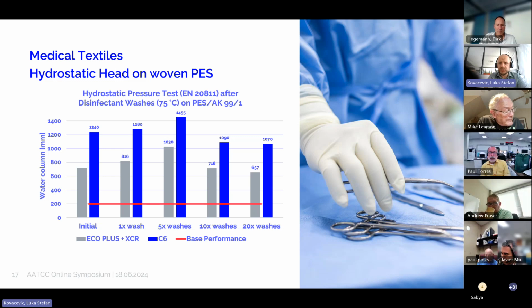Lately, some customers producing reusable medical gowns and drapes have started looking into applying Eco Plus on medical fabric. With medical drapes and gowns, the key performance criterion is the hydrostatic head, and you can see that even here, Eco Plus is not too far from a C6 finish and can sustain a sufficient number of disinfecting wash cycles at higher temperatures.